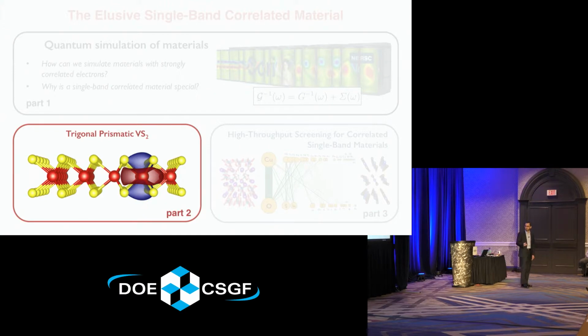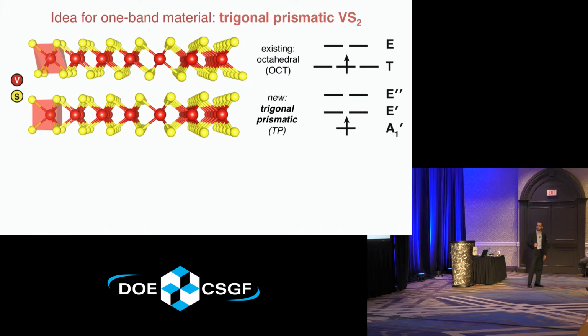So in this next part, I'm going to focus on this specific material, vanadium disulfide, in a particular coordination called trigonal prismatic. So these kinds of materials, in general, have two possible structures. These are layered compounds, so I'm just looking at a single layer here. And you can see on the top we have an octahedral coordination. That's not what I'm interested in because it's higher symmetry. But there's also a distinct coordination called trigonal prismatic. Basically, you just have your metal coordinated by this triangular prism. And the nice thing about this is that from the group theory, we now split the d orbitals into a group of two, and then a group of one. Just this one singly degenerate orbital. So that's exactly what I'm looking for. So I would like to just fill up this orbital halfway, just with one electron.